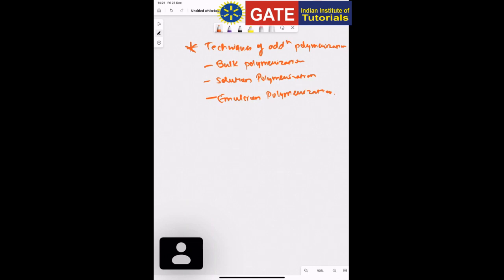So that is what happens in the bulk polymerization reaction, and it becomes very important, to maintain the purity and to avoid any interference of any other component in your final polymer composition, that the solution that you take initially consists only of the bulk number of monomer units, and that cooling is provided appropriately to counter the excess heat generated during the polymerization reaction, because compared to the other ones, which are solution and emulsion polymerization, this is slightly more difficult to handle in case there are any possible hazards associated with the process.